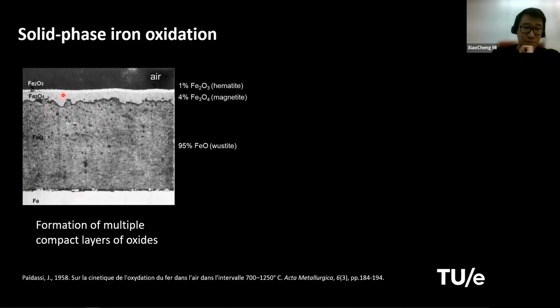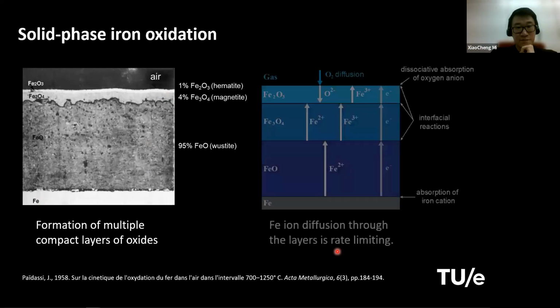You can see that there are multiple layers. There's a very thin layer of hematite or Fe2O3 on top, and then another slightly thicker layer of magnetite Fe3O4 underneath. And then the majority of this oxide scale or oxide layer is the wüstite, FeO, right on top of the iron sample itself. So this sample is exposed to air and kept at a constant temperature. So people can measure the thickness of these different layers over time, and from there they can get some kinetics.